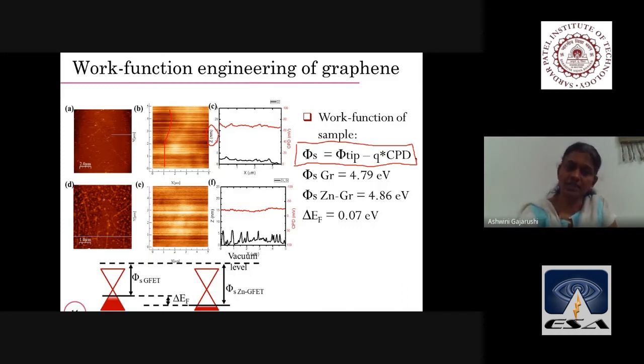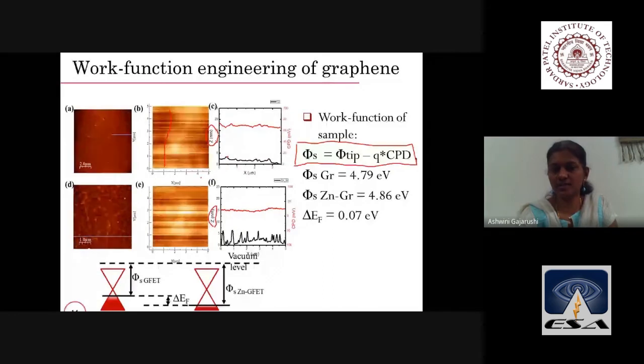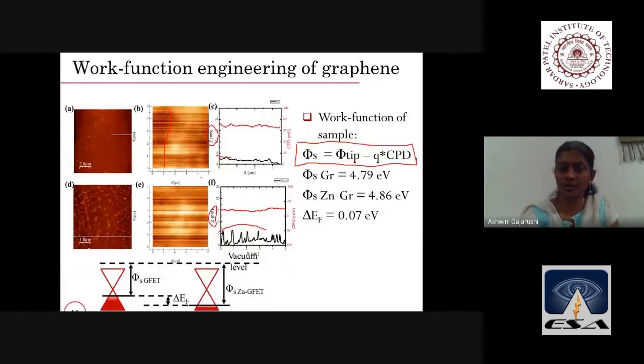So can you see again some doped element on top of it? And because of that, if you see the F image, the height profile has increased to say 6 to 7 nanometer. Earlier it was 2 to 3 nanometer. Now it has increased to 6 to 7 nanometer. So the height has been increased. Why? Because of the doping of this material on top of graphene.